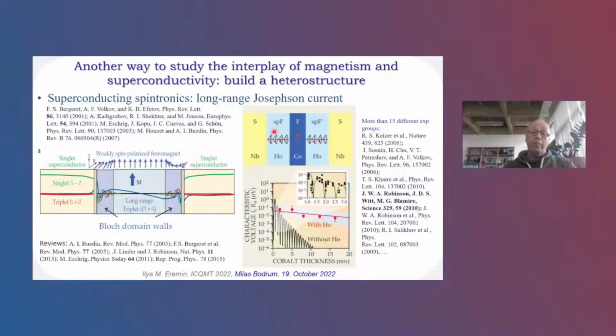And if you have the spiral ferromagnet, then what is happening is that you have a long-range proximity effect, and your current voltage, so your Josephson current exists up to a much longer cobalt thickness, which of course is also interesting because you can also try to polarize this current, and this is the reason why it's interesting for superconducting spintronics.